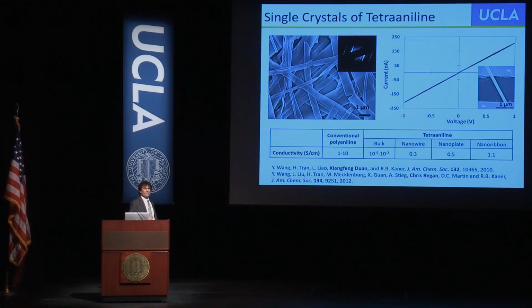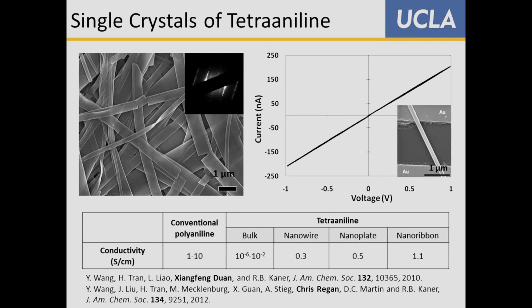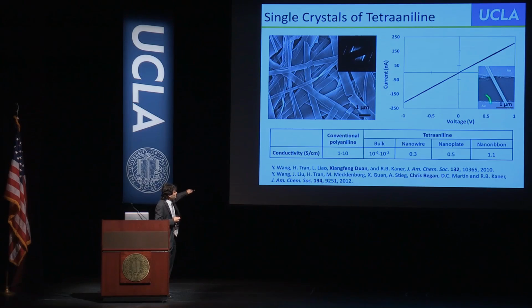I'll point out that we actually wanted to understand the basics of these long polymer chains. And to do that, we looked at the tetramer, which is the smallest repeat unit. And in this work, we made some very nice structures. And we looked at the conductivity. And the way we did this, we went to my colleague Xiangfeng Duan, and he has the ability to put these between 2 gold electrodes. Here's a little tiny nanowire. And we measured it, and it's metallic.